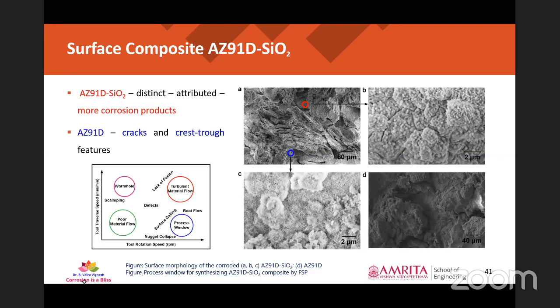One is we have to process the material at high tool rotation speed and at low tool traverse speed to ensure a good defect free region in the friction stir processed zone of composites too.